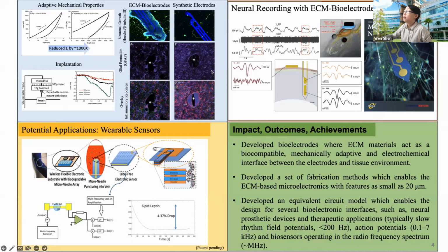One extra step we also did was we also implanted these bio-ECM electrodes in the animal for a much longer time. So these results are after 1 month, but then we have also followed up the experiment and implanted these electrodes in the animal, in the rats for over a year. And then we still see very good biological responses and also neural signal recording responses. So those new results, we are planning to publish that soon.